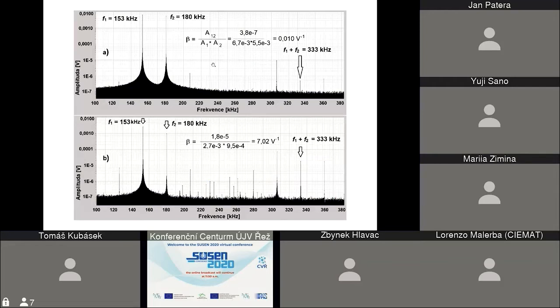This picture shows the difference between healthy and damaged concrete. Healthy is upstairs, damaged is downstairs. This is a graph where you see amplitude and frequency. Two signals emit other signals, and I'm especially interested in the F1 plus F2 signal frequency, where I measure the amplitudes, compare those, and measure the beta coefficient. For the healthy sample, beta equals 1/100 of volts minus 1, and the damaged sample is 7 volts minus 1.